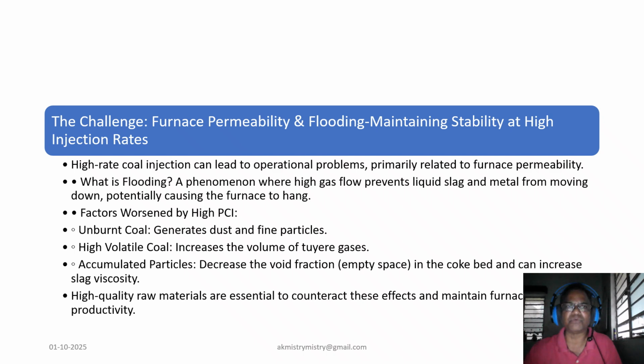High rate PCI worsens this problem in several ways. First, unburned coal generates a high amount of dust and fine particles. Second, using high volatile coal increases the specific volume of gases in the tuyere zone. And third, the accumulation of these unburned particles can decrease the empty space, or void fraction, in the coke bed and increase the viscosity of slag, making it thicker and harder to drain.